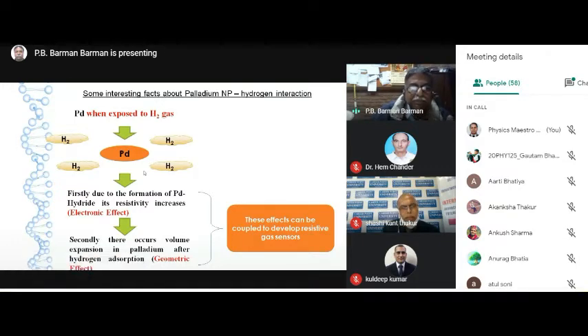And secondly, what happens is that after the formation of the palladium hydride, the hydrogens start basically interfering or going inside the palladium, resulting in expansion in volume, resulting in the swelling of the particle.